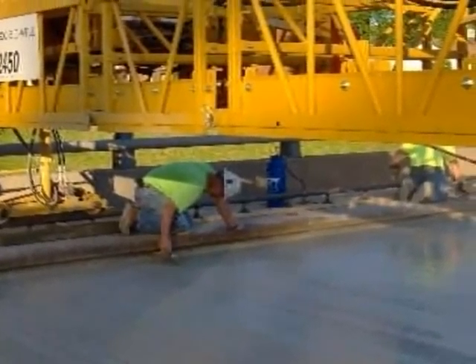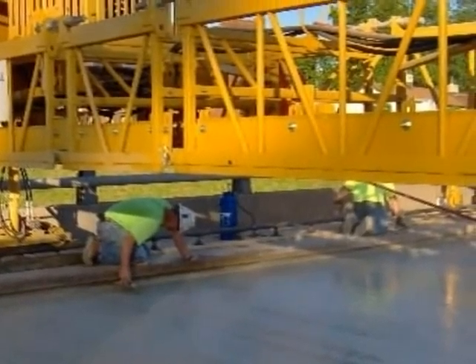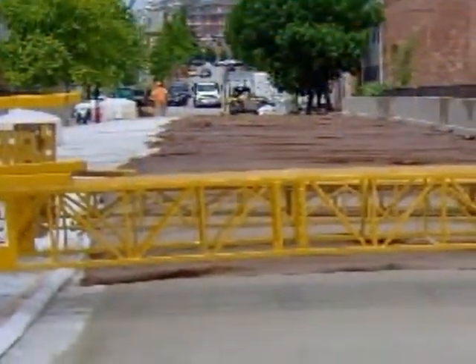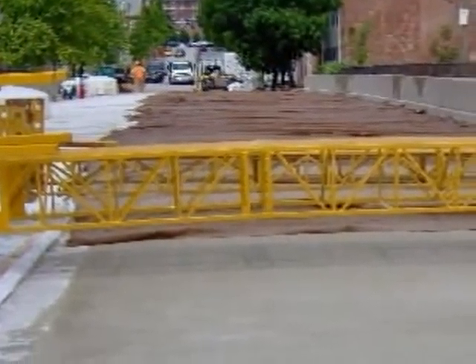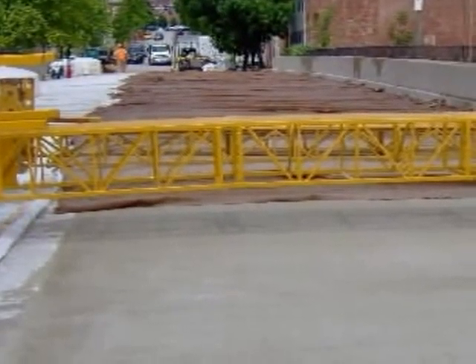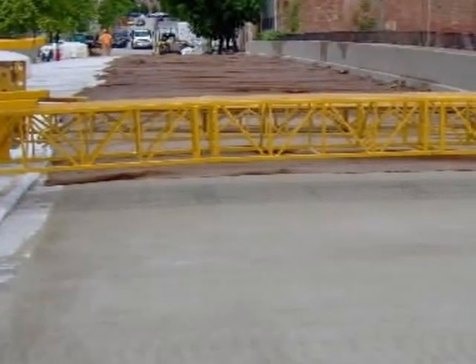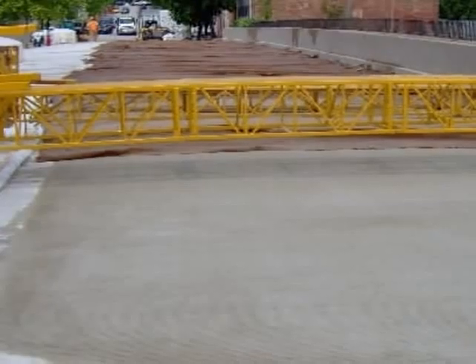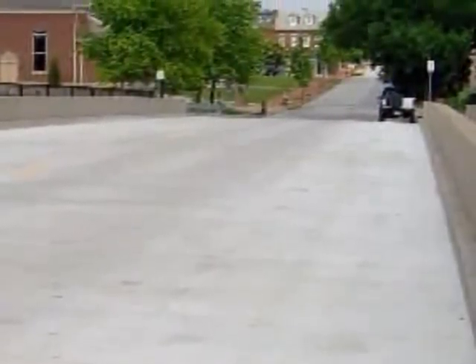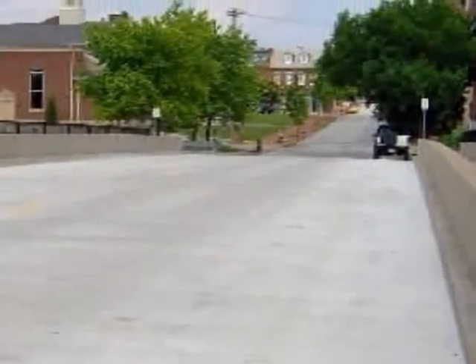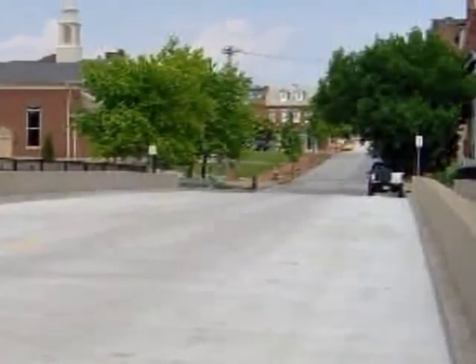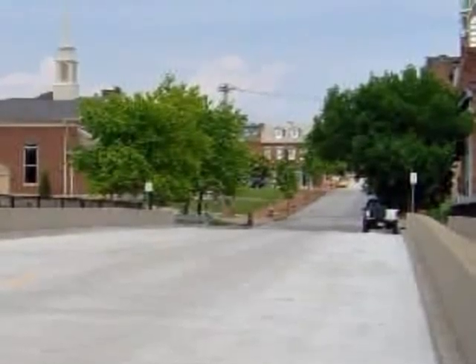The rapid-set low-cement concrete was produced on-site using mobile volumetric mixers at a rate of 10 cubic yards per 30 to 40 minutes. Reloading was done within a mile of each bridge, and recharge averaged about 30 minutes per round trip. A 9-inch slump at discharge allowed easy placement, and the Bidwell finisher worked well with the concrete.